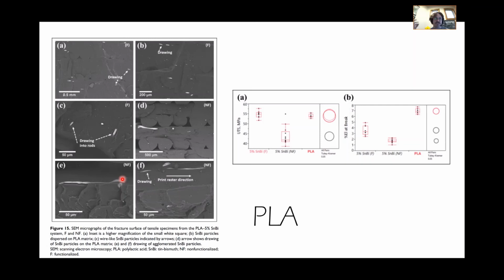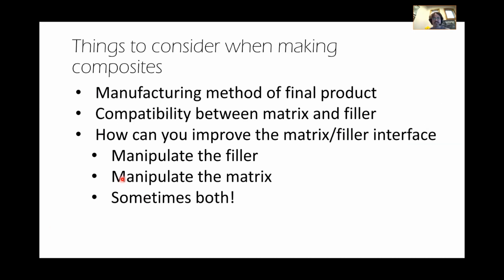So it's a very, very complex subject, if you will. Things to consider when making composites: the manufacturing method of the final product, compatibility between the matrix and filler, how you can improve the matrix-filler interface - so three ways, manipulate the filler, manipulate the matrix, or sometimes both. And sometimes it doesn't work out if you do both strategies.